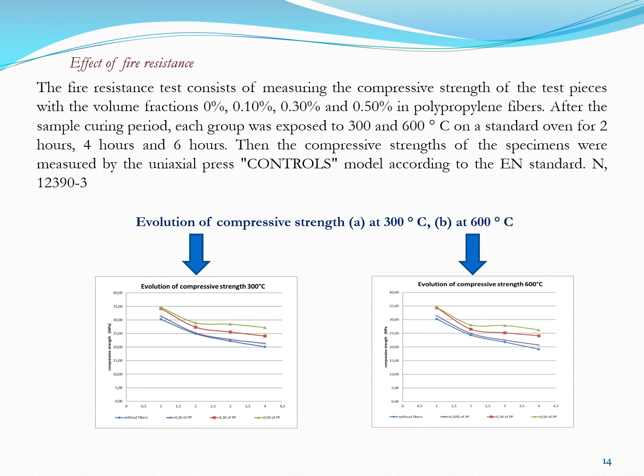For different temperatures, the composite with 0.10% fibers exhibits the lowest loss in compressive strength. This loss is increased at 6 hours of exposure for the two temperature ranges. In the case of concrete with polypropylene fibers, the fiber melts at 160 degrees Celsius, creating voids in the concrete. Vapor pressure is released in the newly formed voids, and explosive spalling is greatly reduced.